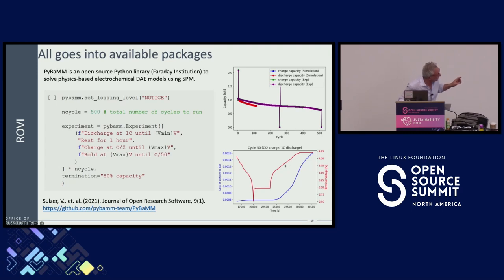You can see that a lot of the degradation happens when your phone is almost completely charged, right? Now if you plug your phone in, the iPhone will tell you that it's going to stop charging and will finish charging before you're ready to use it. It's most likely because of curves like this, where they know that a lot of the degradation will happen when the battery is at the top of charge, and what's the point? If you're sleeping, you're not going to use it, right?